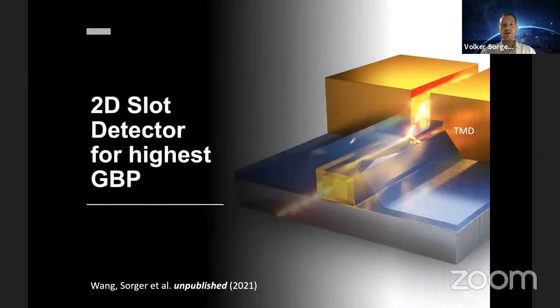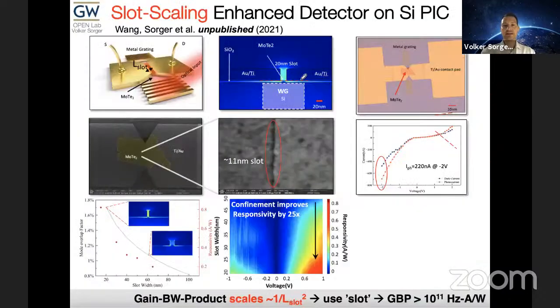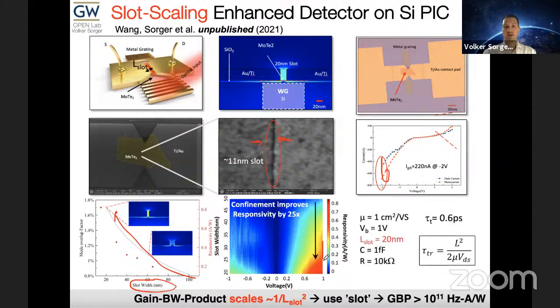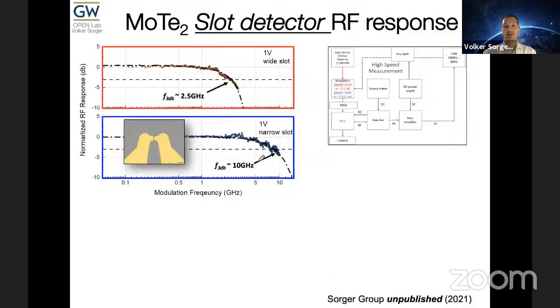And then some very nice work that is still unpublished is where we put a TMD material into these slots. We make these very, very narrow slots to utilize this high gain bandwidth product. Here's the IV curve. We see we get a nice photo response. And indeed, if we reduce the slot distance, we are able to get a very high overlap factor and a very good mobility, a very good responsivity. We experimentally showed we can get up to 10 gigahertz fast devices like this, and they're significantly faster than for a long channel device.